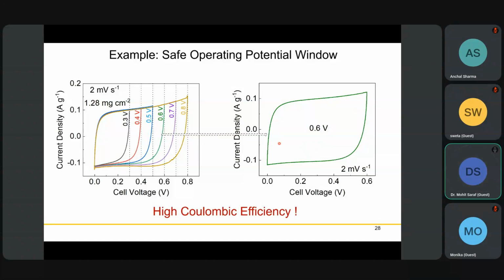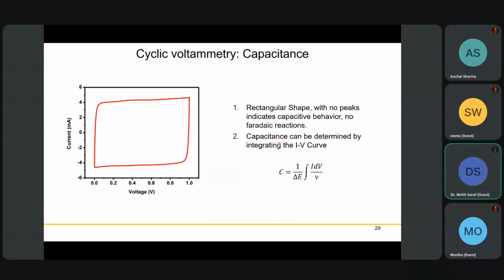electrochemically stable operational voltage. And then while calculating capacitance, we have to take into account the nature of the process happening. For example, if it is a double layer capacitive material with double layer kind of rectangular behavior, we can simply use this formula. It's typical of double layer materials where there are no sharp peaks. Basically you are just integrating the area under the curve and then dividing it by the scan rate. Delta is basically the potential cutoff, from 0 to 0.95, whatever it is.